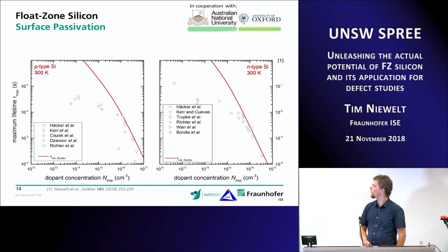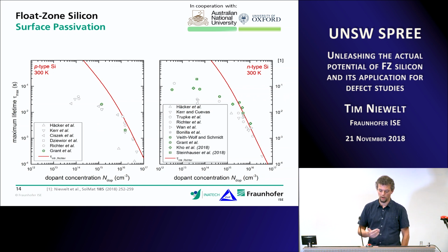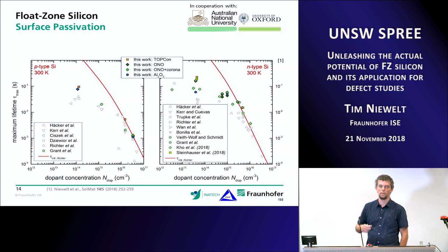Some more results or some more graphs to put our results into perspective. So here we collected the best reported lifetimes, I think, until 2015, and these points are more recent record lifetimes, also of groups that we are working with, and that are also applying such a pre-treatment usually to their wafers. And these points are the points from the study that I was showing you earlier, this demonstration study. And as you can see, on all the materials that we've tested, we are getting world record lifetimes. So this really indicates that this pre-treatment that we are doing to our float zone material is really improving the material beyond what other groups have seen in the past.